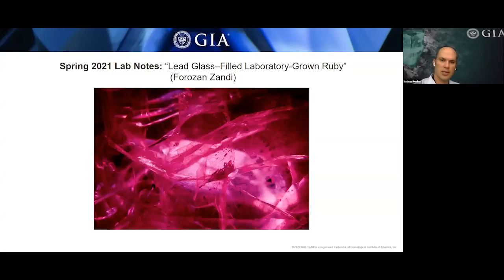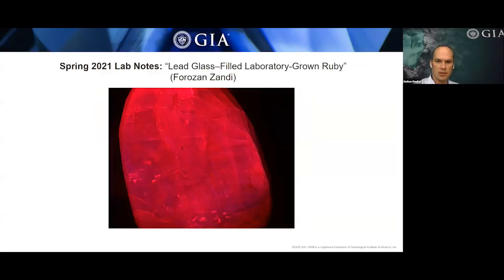In a stone like this, it's pretty difficult to see the curved striae, but using diamond view fluorescence imaging, we were able to clearly see the curved structure of the flame fusion growth. With the lead glass filling, this stone was most likely quench crackled to induce the fractures and then subsequently filled. Maybe the intention was to make a more natural looking synthetic or lab grown ruby, but it still seems like quite a lot of work to produce such a stone.